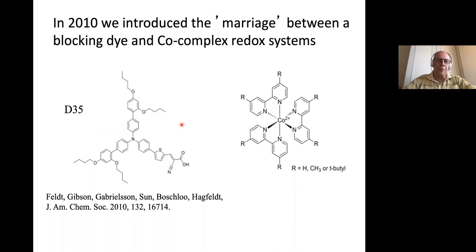And Eric Gabrielsson, a PhD student at the time, he introduced these alkoxy groups with the idea to avoid aggregation of these dyes, which is a problem for organic dyes. So the initial idea was to introduce these alkoxy groups so they are spreading out and you don't form the aggregates. What we found with this dye was that this dye itself passivated the surface very well. So we thought maybe with this dye we have a chance to work on something else than iodide.